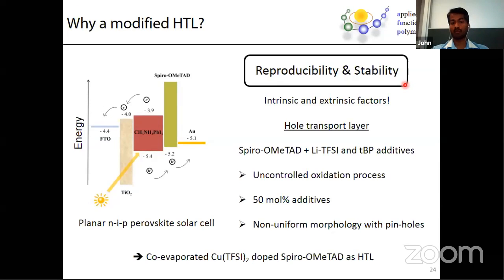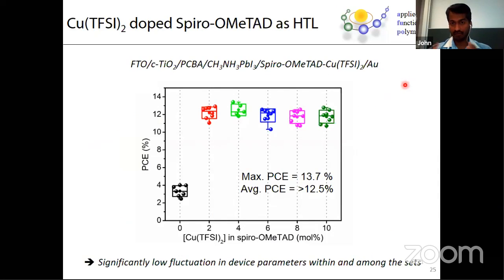So that's why we thought, why don't we go with our co-evaporated copper TFSI doped spiro-OMeTAD as a hole transport layer. In this case, I'm just going to show the end results of our devices. So this is the device configuration. We took FTO as one of the electrodes, and then, similar to the slide that I showed before, titania as the n-type material, and PCBM, a derivative of fullerene, as an interfacial layer, and then perovskite, methylammonium lead iodide, and then spiro-OMeTAD doped with copper TFSI, and finally another electrode, gold, on top of it. So with increasing dopant concentration, we actually obtained very good efficiency, something close to 12.5% on average.